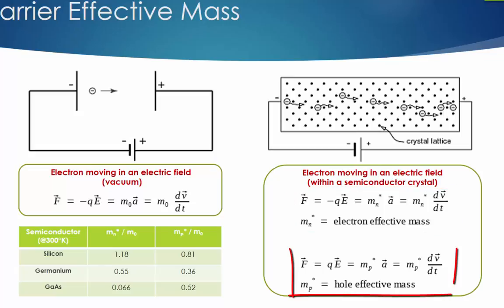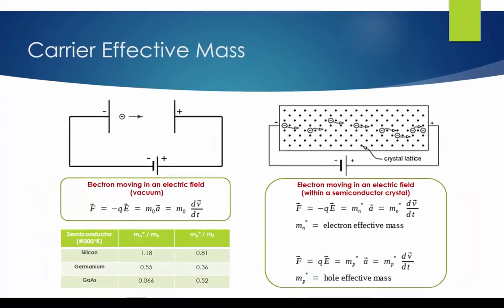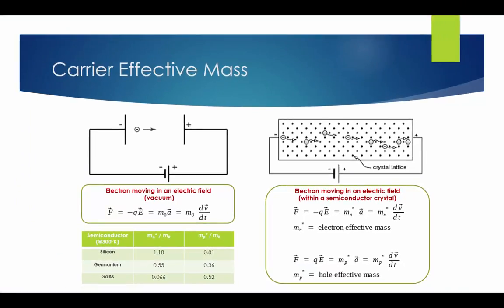The same concept also applies to holes, which have a positive charge. The hole's effective mass is represented by MP asterisk. The effective mass concept includes both the internal crystalline field and the quantum mechanical effects. So now we get this conclusion. The electron and holes can be treated as classical particles when we use their effective mass.